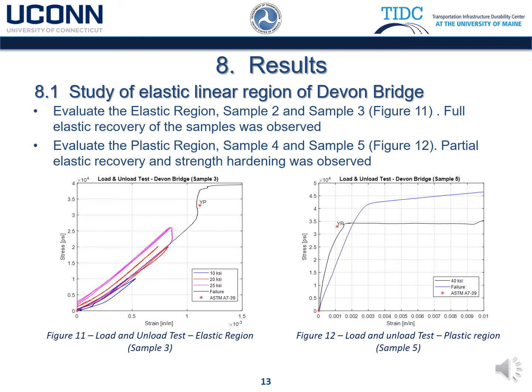Full elastic recovery was observed in sample 3 and sample 2. Sample 4 and sample 5 were loaded and unloaded to the plastic region to understand the plastic behavior of the material. Figure 12 shows the stress-strain plot of sample 5, loaded to 40 KSI, unloaded and reloaded to failure. Partial elastic recovery and strain hardening were observed on those samples.